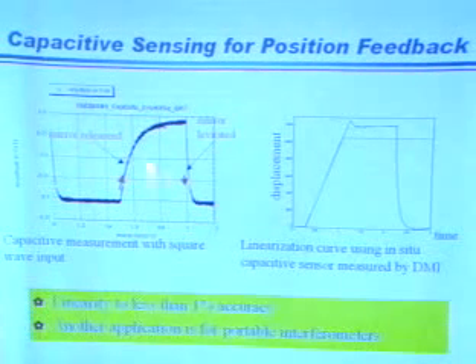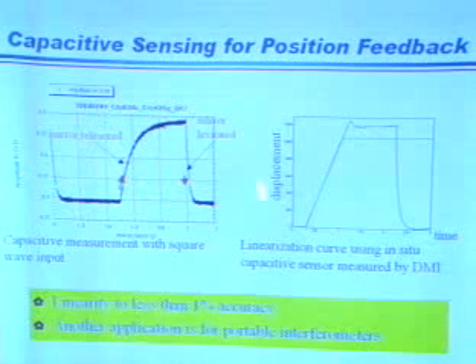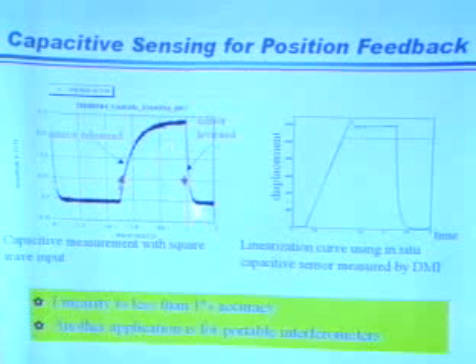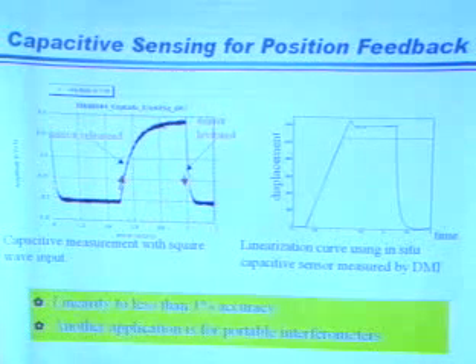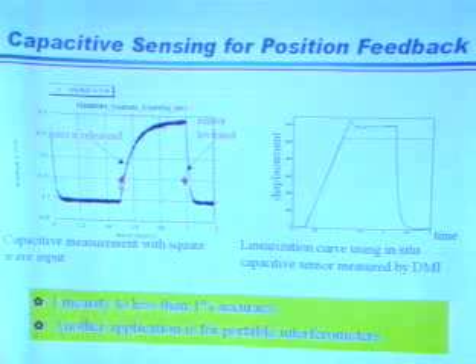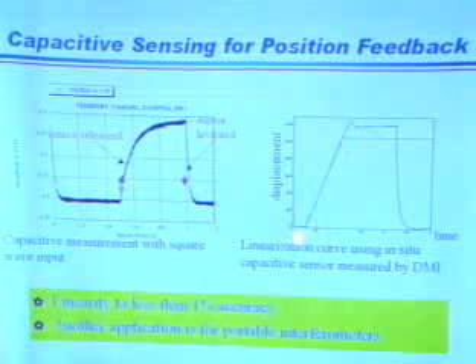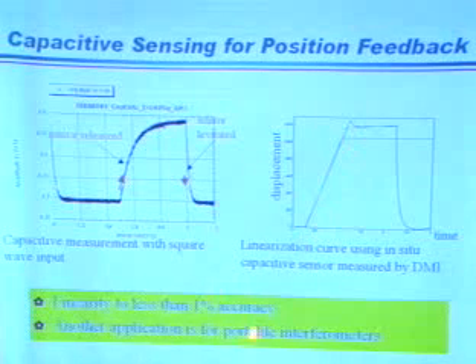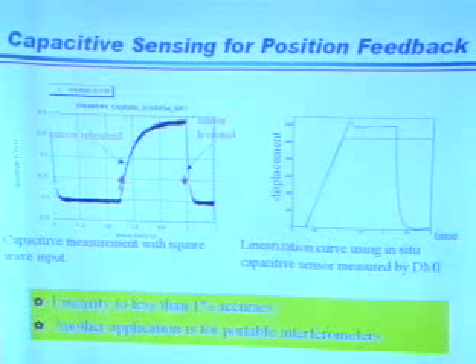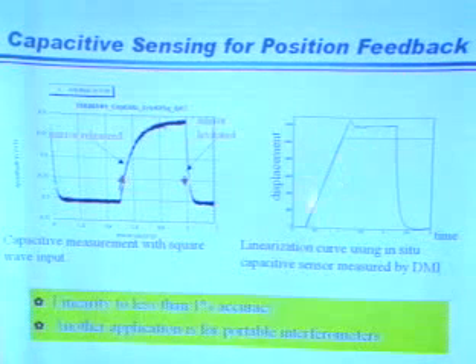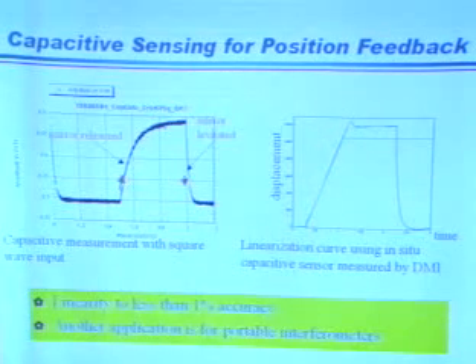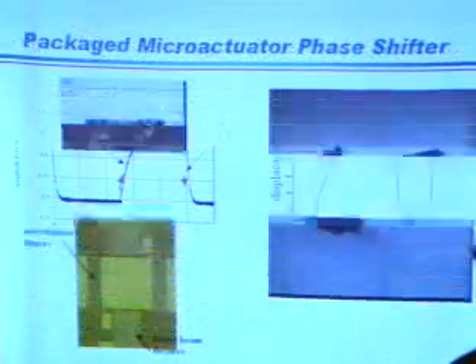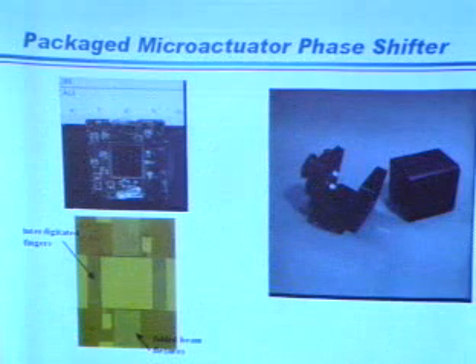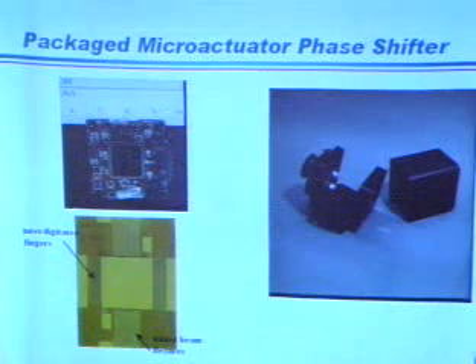It has a very, very slow response time. But when you're pulling it up, you actually get a much faster response time. The bottom line is it's a nonlinear effect. Using that capacitive feedback, we were able to get accuracy down to less than 1%, which translates into 2 to 3 nanometers of accuracy control, and that was very critical for that interferometer. And that's the package and the final mirror, on the surface mounted package.